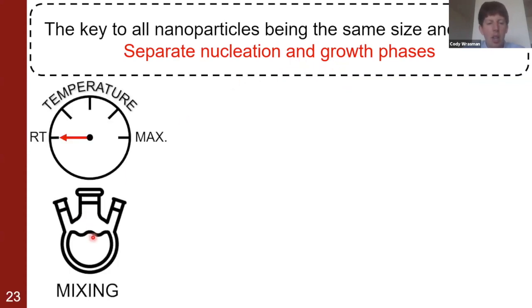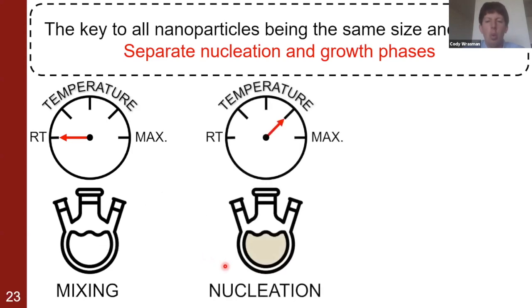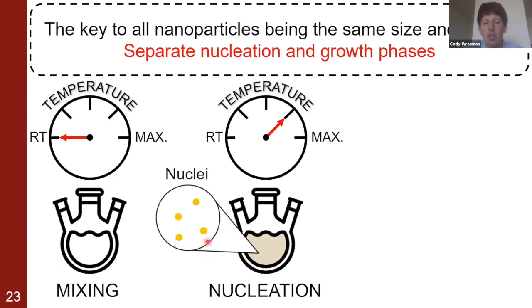So if we look at a synthesis flask at room temperature, with all of the ingredients mixed, they tend to be relatively clear liquids. And if we were to look at them very closely with TEM, we would see nothing. There's no nanoparticles formed at room temperature. Once we start heating the reaction up, though, once the nanoparticles start to form, you'll notice that the synthesis solution actually starts to change color rather dramatically, typically moving from these clear colors towards black. And if we were to look at TEM, once this nucleation process starts, we see these very, very small.